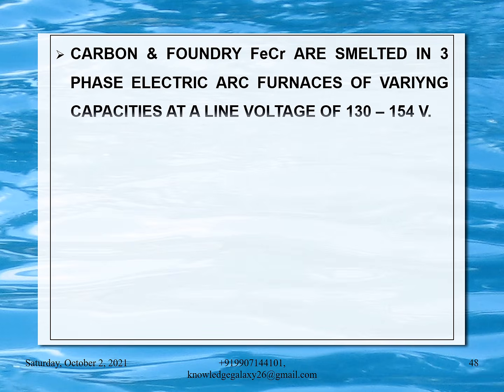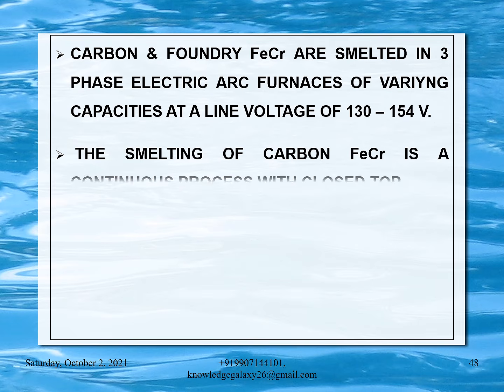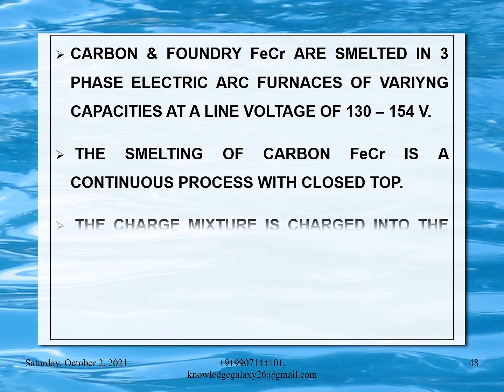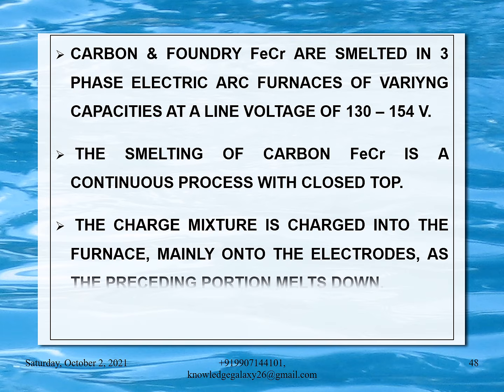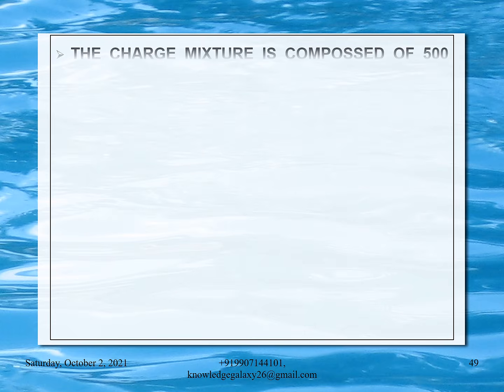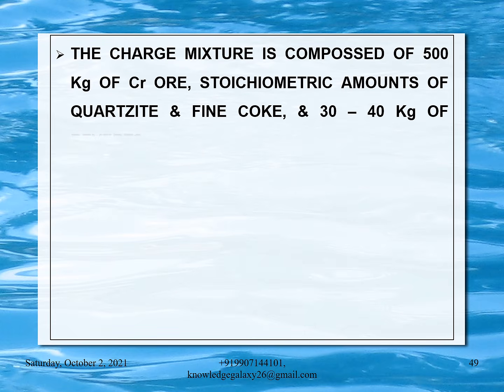Carbon and foundry ferrochrome are smelted in three-phase electric arc furnaces of varying capacities at a line voltage of 130 to 154 volts. The smelting of carbon ferrochrome is a continuous process with closed top. The mixture is charged into the furnace mainly onto the electrodes as the preceding portion melts down. The charged mixture is composed of 500 kg of chromium ore, stoichiometric amounts of quartzite and fine coke, and 30 to 40 kg of reverts.